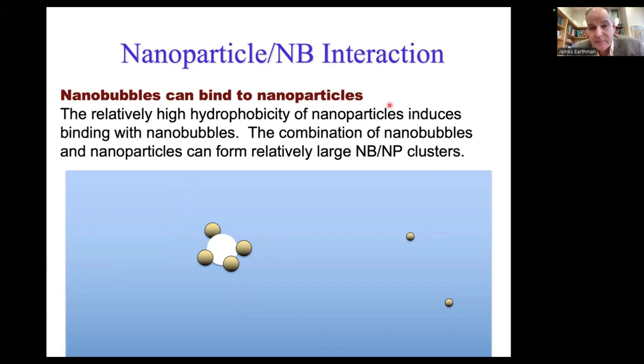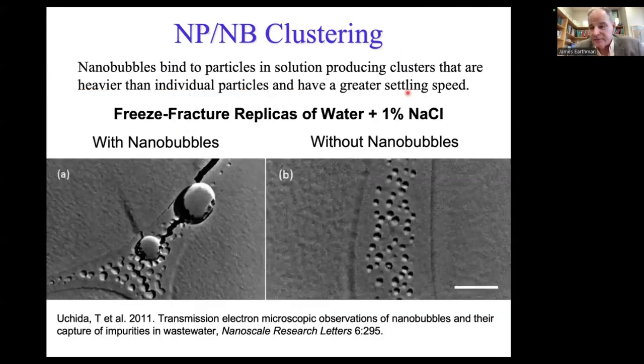So this hydrophobic force at this size scale is really powerful. Now, these particles may not be stable. They may be embryos. They could be at the solubility limit of this solid, and they could just be forming and dissolving over time. But if they bind to a nanobubble, their surface tension is going to go down, and they're going to become stable. And if we keep doing that, we can force the concentration of that solid to below the solubility limit.